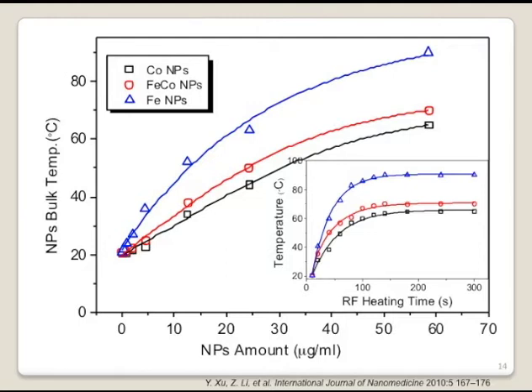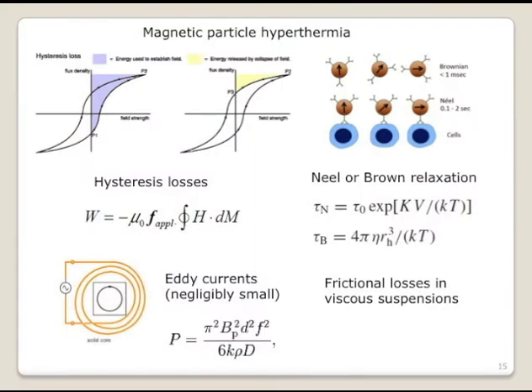The temperature also increases with the nanoparticle amount. The more the material, the higher the temperature. So among the 3 different types of nanoparticles, iron nanoparticles can reach an even higher temperature. Okay, what's the reason? Because the iron nanoparticles are the most efficient in heating. We need to look at the mechanism.